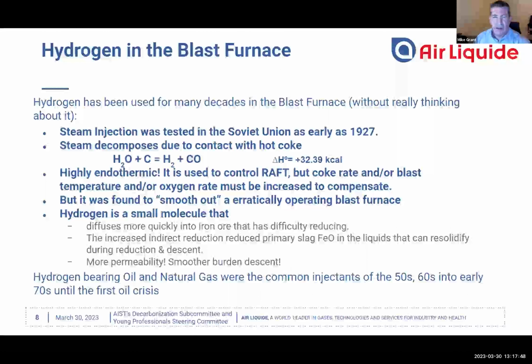And the reality is we've been injecting hydrogen in the blast furnace for many decades. And this was steam injection, of course, first, I think, documented in the Soviet Union in the 1920s. By injecting steam into the tuyeres of the blast furnace, you get a reaction with the hot coke inside the raceway, and this makes hydrogen. And of course, this is very endothermic and requires a coke increase to cover the endothermic energy that is being absorbed. But the hydrogen that was created was found to actually smooth out the operation. So a furnace that's moving or descending erratically, a little bit of hydrogen actually helps smooth it out.